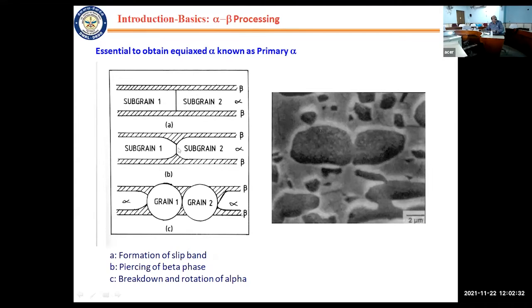And then what it does, the beta phase pierces the alpha phase because of the surface tension effects. And then when you heat it, the elongated grains of alpha become rounded. And once you do solution treatment in the alpha plus beta regime, you can give globular alpha. It is required. I will show you why it is required. And this is one of the examples where beta is entering and breaking off the lamellar alpha.